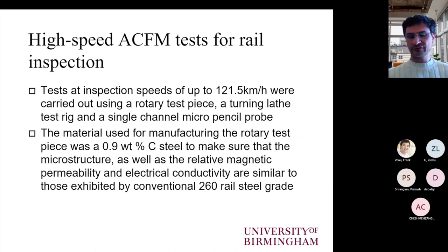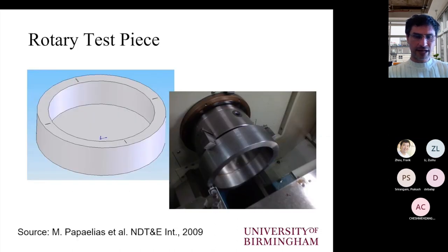In order to simulate the steel grade that is used for modern rails, we used the 0.9% carbon steel, which is not that far off from the 0.8% 260 rail steel grade, which is currently used for manufacturing rails and installing it on the network. Even though some older rails may be 220 grade, which is 0.4, 0.5, 0.6% carbon max.